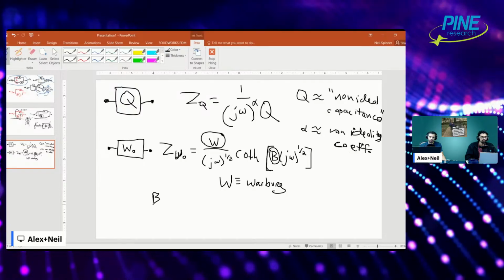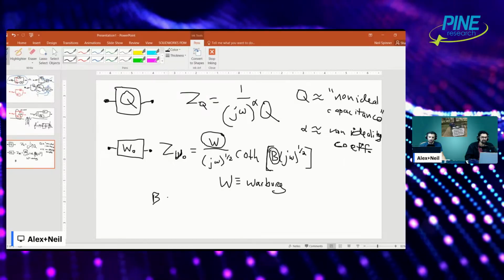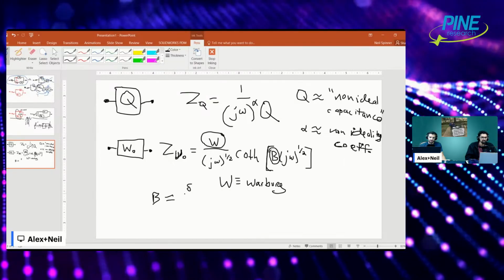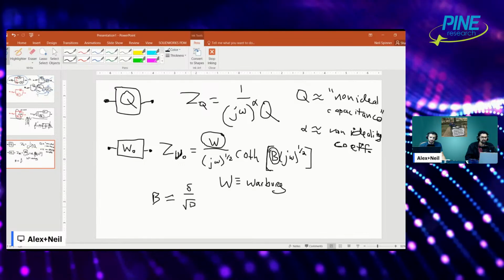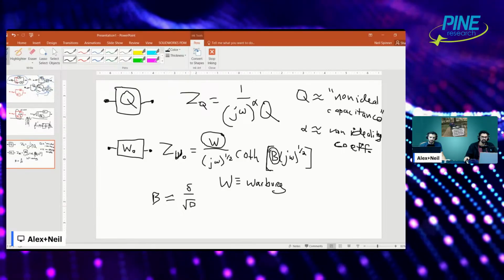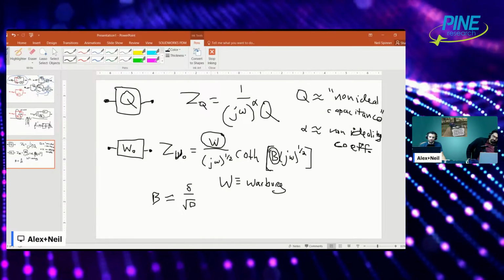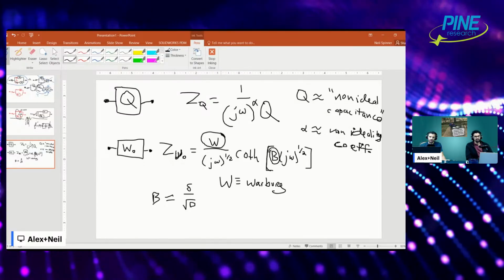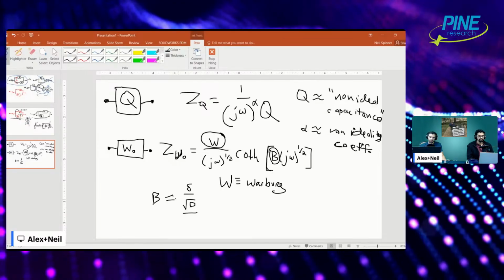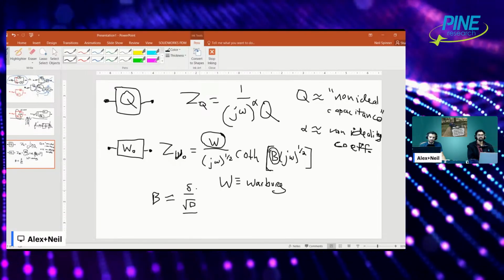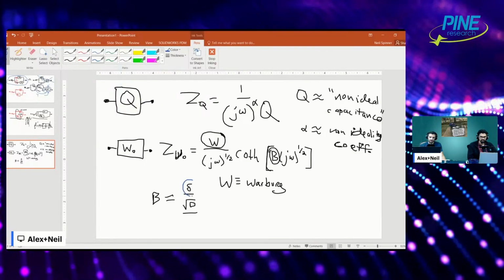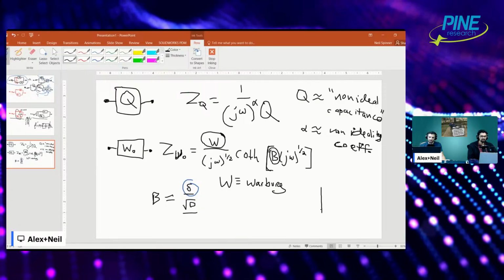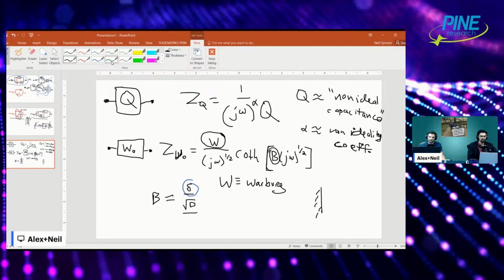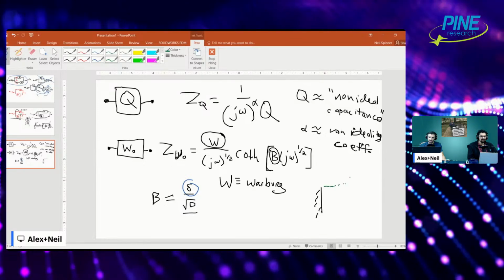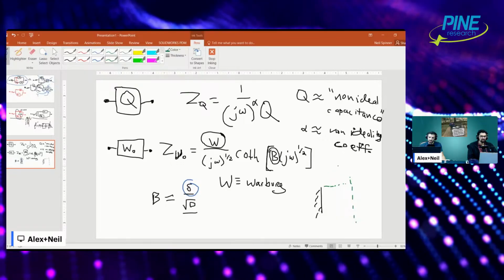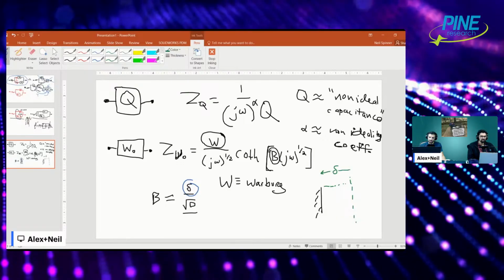B, on the other hand, B is equivalent to what's called delta over the square root of D. So D is the diffusion coefficient. So the diffusion properties, I guess you'd say, are related to both of these constants, W and B. For instance, the diffusion coefficient plays a role in B, but mainly what B is used as a measure of is this. It's the diffusion layer thickness. So if I have an electrode surface with a Warburg open, I have a diffusion layer of some set thickness. This diffusion layer thickness is delta.